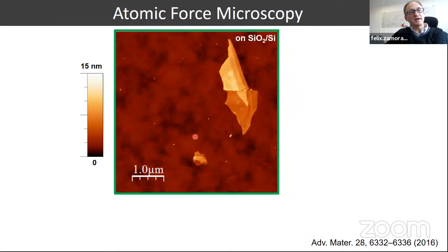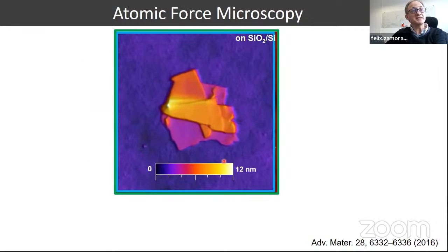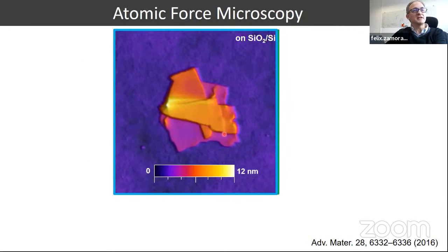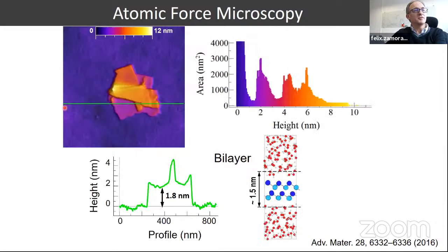Let's zoom in on this particular small set of layers, and as you can see here, those are really small in thickness. If you check this height profile, this line in green, you can see that this violet layer shows a particularly small thickness, 1.8 nanometers, which nicely corresponds with the isolation of a bilayer. Taking into account that this is at ambient conditions, we should have some additional layers of water on the top and bottom of this nanolayer. So this demonstrates that we were able to isolate bilayers.